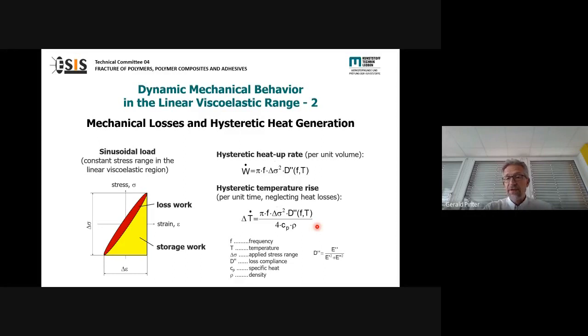So, for example, if you're testing a polyethylene material with a glass transition below 0 degrees Celsius, and for example, on polyamide materials, where the glass transition typically is in the range of room temperature or a little bit above, typically, therefore, you have a much higher temperature increase if you test polyamide 6, polyamide 6,6 materials in comparison to polyethylene. So in testing, of course, you have to consider this and to test polyamide at much lower frequencies than, for example, you can use for polyethylene.